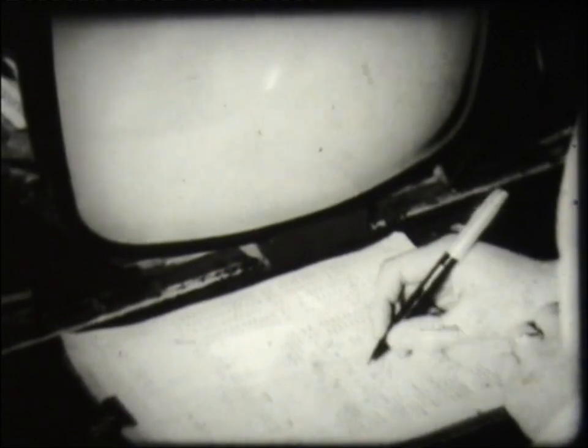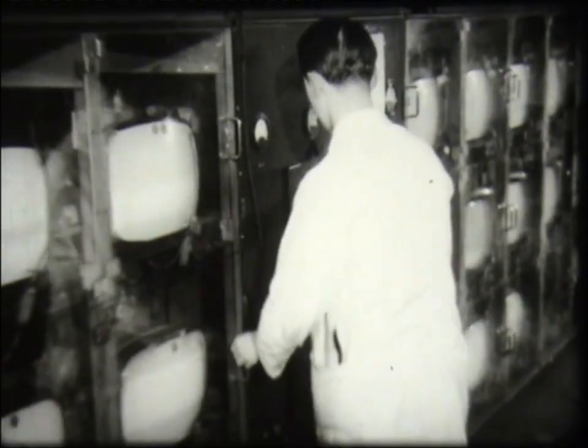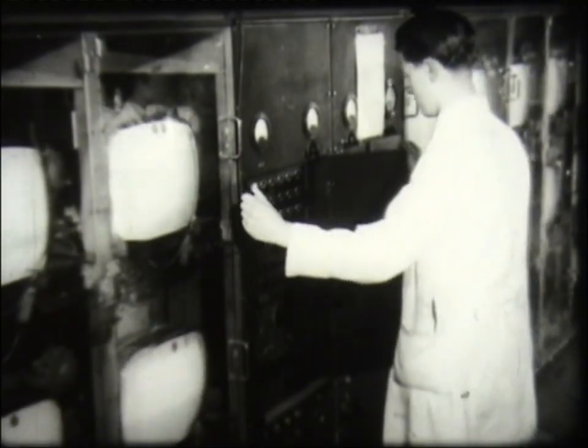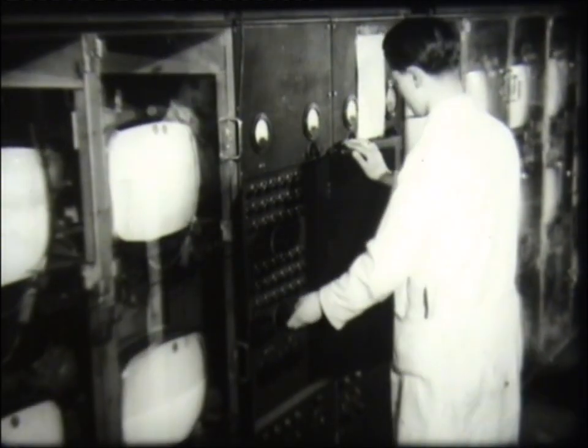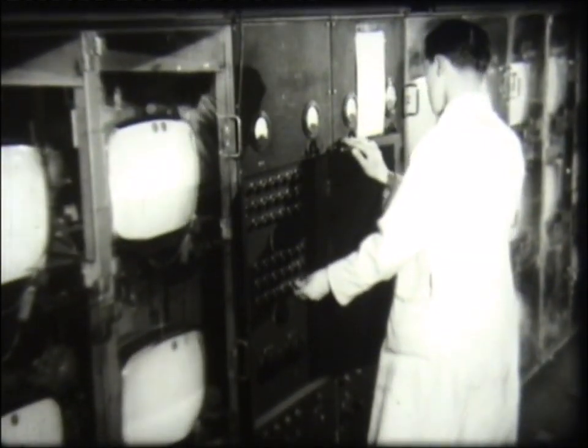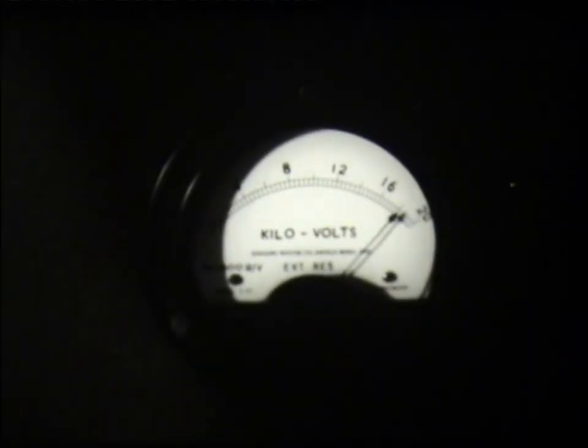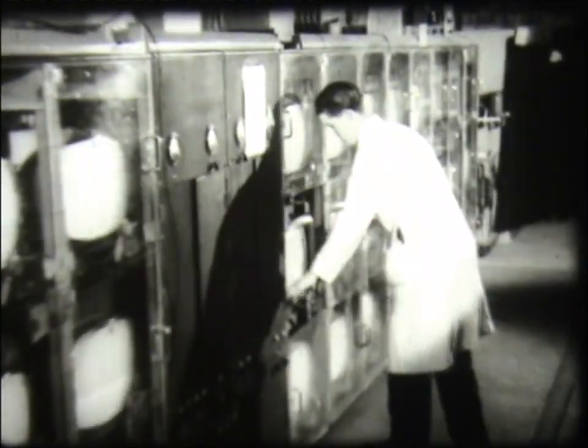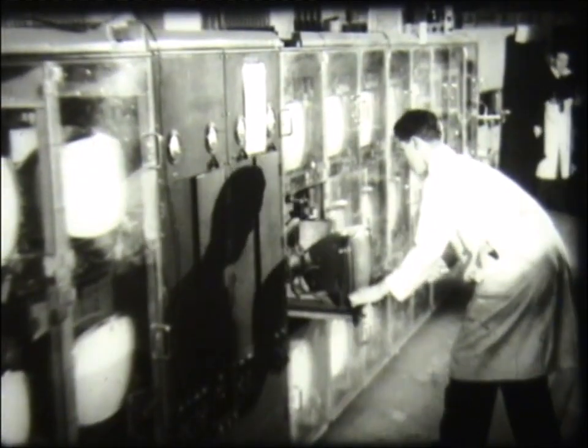A proportion of the tubes is submitted to tests to ascertain their expectation of life and to reveal the cause of ultimate failure, no matter how long life may be. To speed up these tests, the tubes are run at excess EHT voltage and excessive beam current, so that in a few months they have done the equivalent of several years' normal service. Service conditions are simulated by switching the tubes on and off at intervals, and once a week each tube is taken from the rack and its characteristics rechecked.